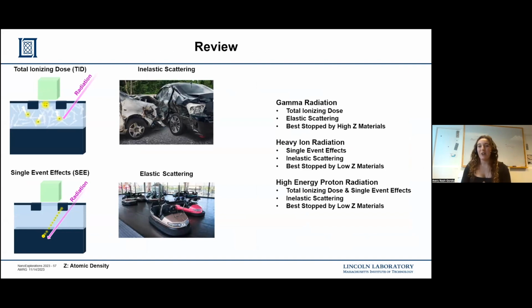Gamma radiation causes total ionizing dose. This is the long-term degradation of your electronics over the mission life. Because it's dominated by elastic scattering, it is best stopped by high atomic density materials. Heavy ion radiation causes single event effects, the instantaneous shutdown of your electronics. This is dominated by inelastic scattering, so it's best stopped by low Z materials.